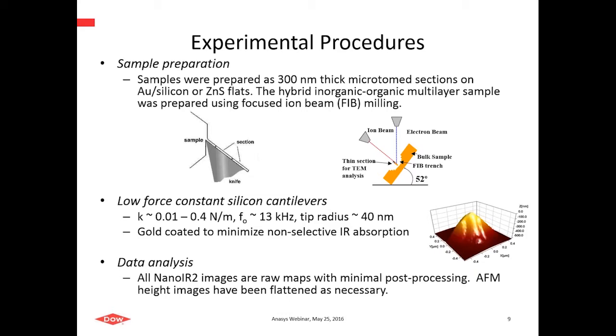And I'll show you one example where we had a hybrid system we made that contained both organic and inorganic materials that were prepared on a silicon wafer substrate that's damaging to the knife. We couldn't microtome that sample, so instead we used focused ion beam milling as a method to prepare it and pluck a section and then turn it on its side for analysis.